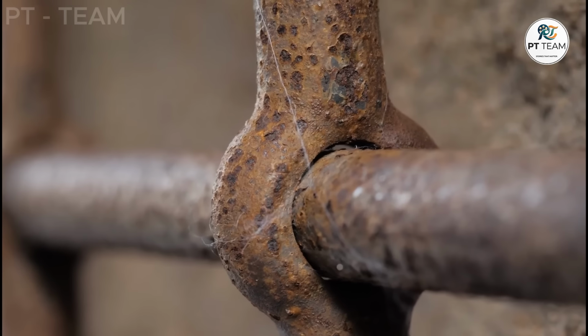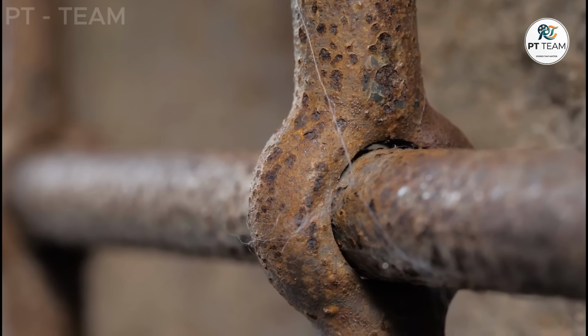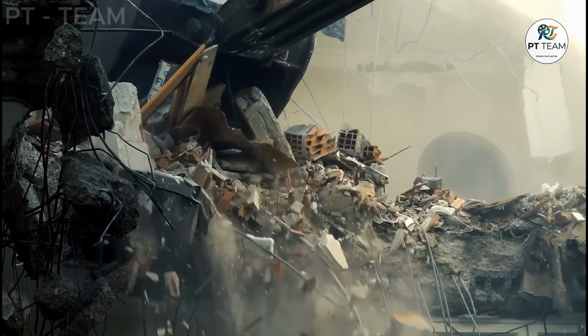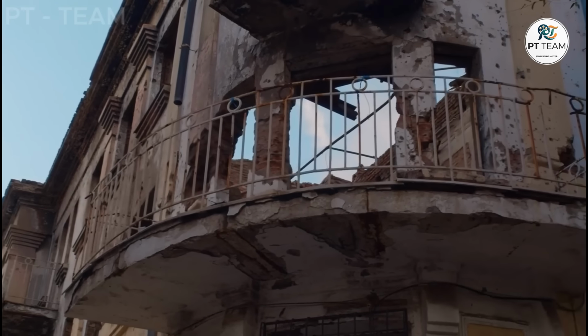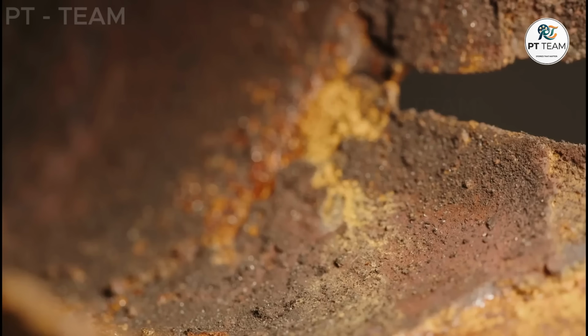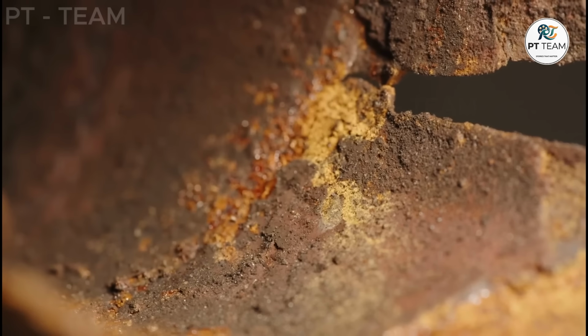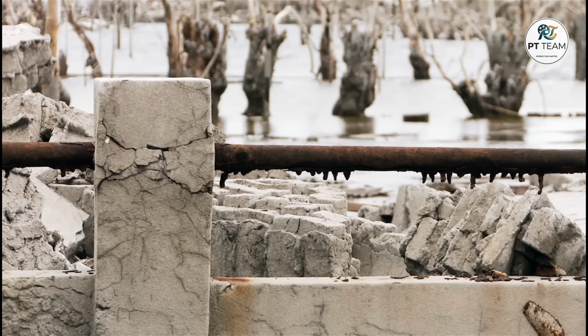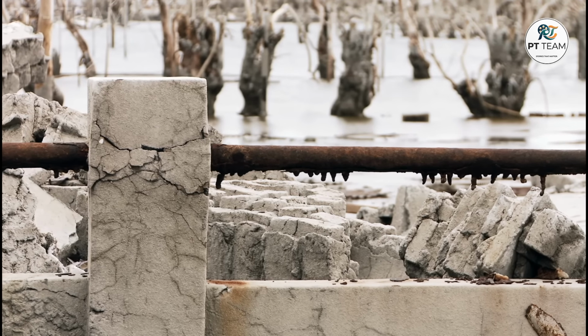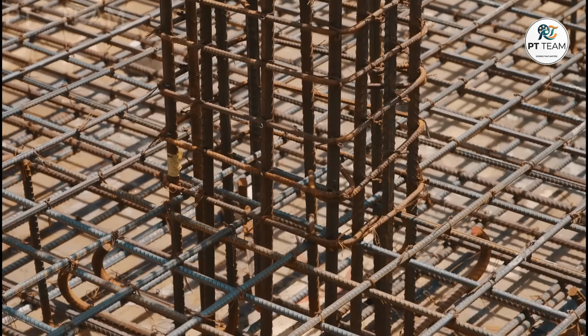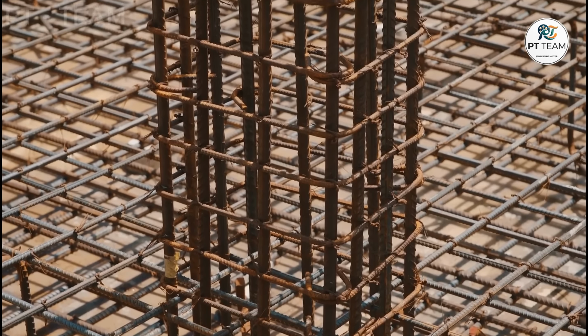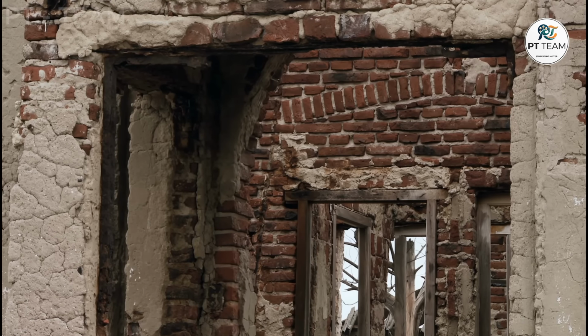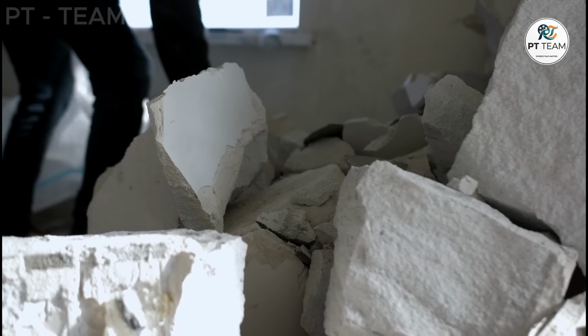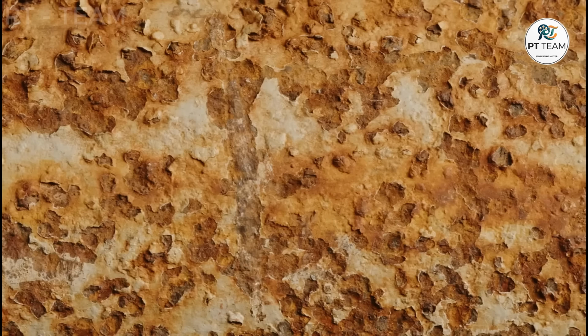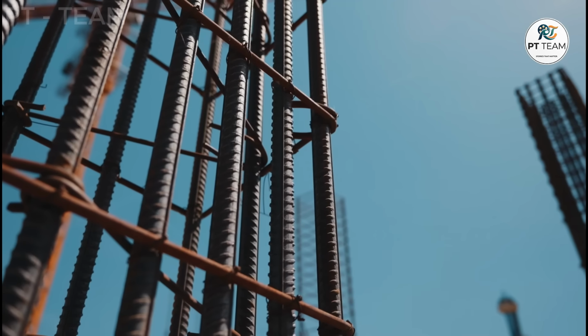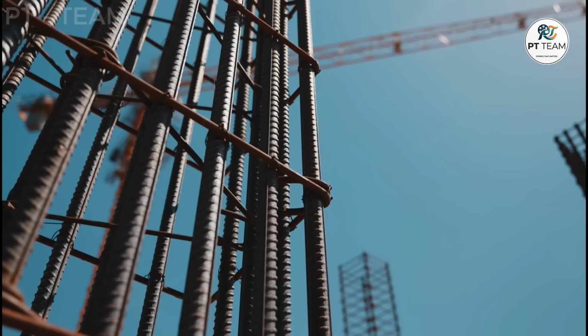As the rust continues to accumulate, the tensile stress builds up until it exceeds the tensile strength of the concrete. The material has no choice but to tear itself apart to relieve the pressure. A microscopic fracture develops internally and slowly propagates toward the exterior surface. When the fracture finally reaches the outside air, a visible crack appears on the facade. The steel is literally pushing the concrete out of its way. If the corrosion continues unchecked, the cracks widen until entire chunks of the concrete cover break off entirely. This event is known as spalling. The rusted steel skeleton is suddenly exposed to the open air.